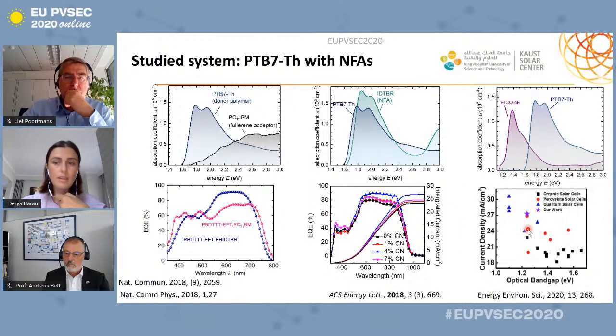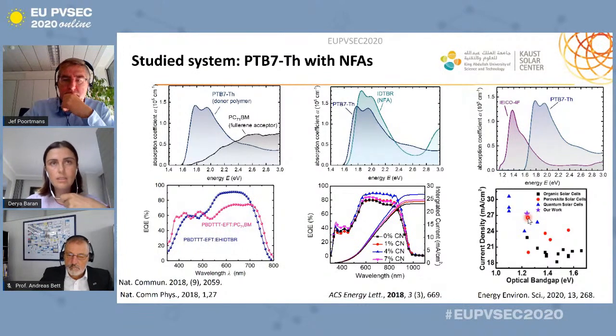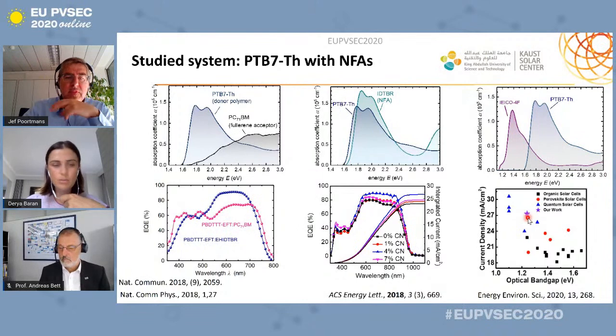So why I show this is very interesting, because the photocurrent from this IEICO-4F is about 26 milliamps from a single junction solar cell. And when you compare it with different technologies, it's quite impressive for such a low band gap material, and again, such a high current density. So with OPV now, we can achieve very good voltages and we can have competitive photocurrent densities. And now the question would be, maybe, to maximize the fill factor. And then, as you see, it is not that bad and can also be competitive with different emerging technologies.